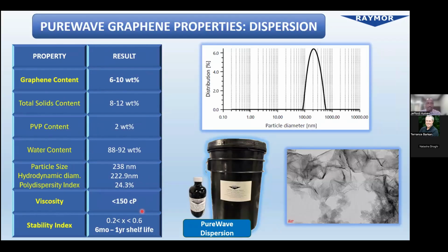Apart from just producing the material as a powder, we're also very proud that we're able to disperse our powders into an aqueous dispersion at very good loadings. We're able to obtain graphene loadings of 6 to 10 weight percent.